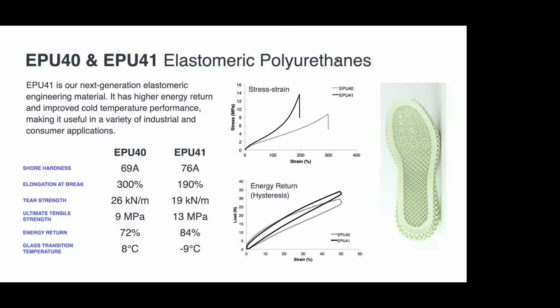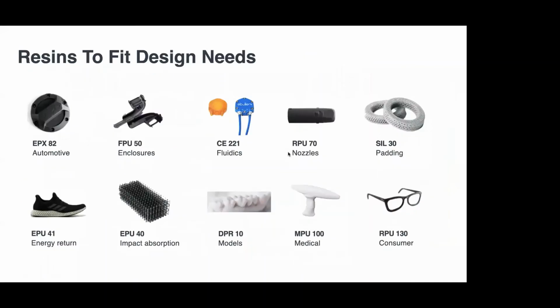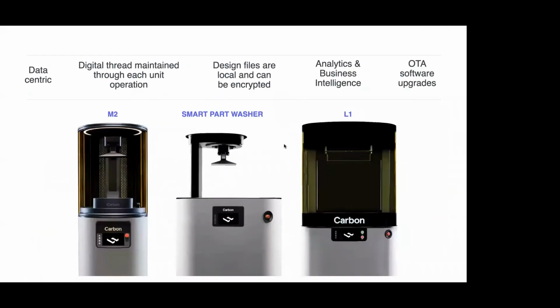All right, so you can do this with polyurethanes and elastomers and get a wide range of properties associated with that. And this really opens up the opportunity for doing a wide range of different polymeric materials using this approach. Part of this too was extending it to a technology for the printers, and developing a printer with 75 micron pixels and 160 micron pixels with different build areas. The L1 is 5 times the build area of the M2.